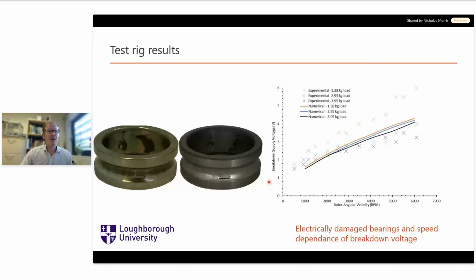And the crosses here are the experimental data points, and the lines show the numerical model data points. So there's a couple of things which are of interest here. As expected, as you increase speed or decrease loads, the EHL film thickness will increase. And as a result of that, the electrical field strength in the contact decreases, and it means you require higher voltage to break the lubricant down electrically, to overcome the dielectric strength of the lubricants. The other thing to notice here, which isn't immediately clear from the graph, is that to fit these lines to the experimental data, we had to use a dielectric strength of the lubricant which was significantly higher than that provided on the data sheets.